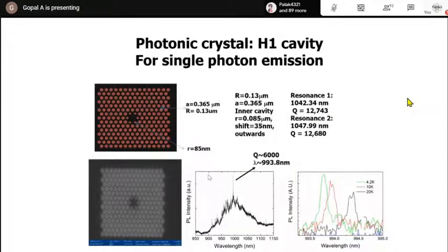So you can also use it, for example, what we work on in the lab is we put a single nanoparticle in the center of this photonic crystal. So we remove the central hole, or in a periodic structure of rods we remove the central rod, for example, and then modify the neighboring ones so that we get a small cavity here. Okay, so in that cavity, we put one nanoparticle of like 2 or 5 nanometers, less than 10 nanometer size. We put it precisely at this position. Then we tune the band gap of the semiconductor nanoparticle. So the cavity resonance and the quantum dot emission are matched together so that we get a huge enhancement in emission, and we can use it for generating single photons.